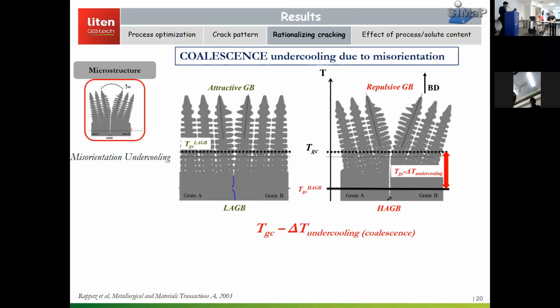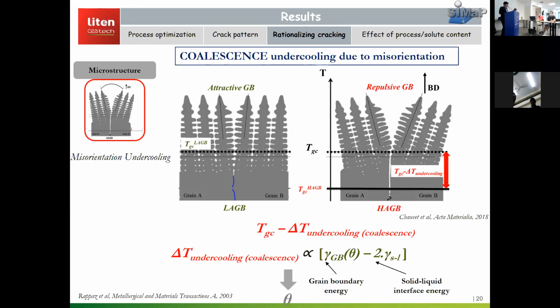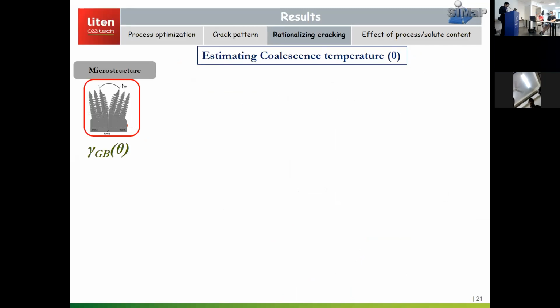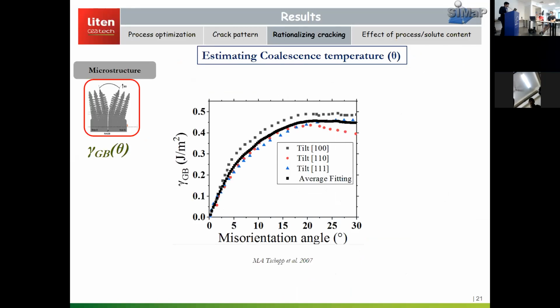This undercooling in coalescence, according to the coalescence model of Rappaz, depends on the grain boundary energy and the solid-liquid interface energy. So in order to estimate the coalescence undercooling, we need an idea of the grain boundary energy and the solid-liquid interface energy. So let's start by estimating the grain boundary energy as a function of misorientation.